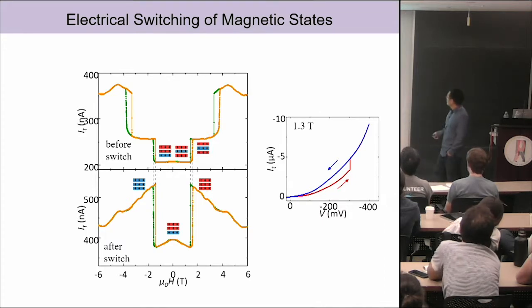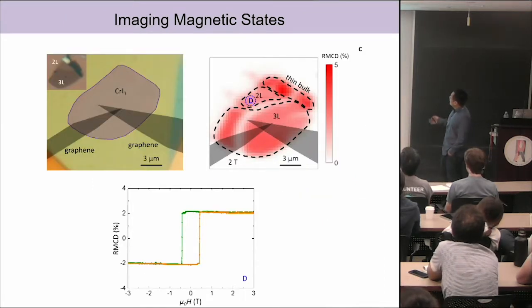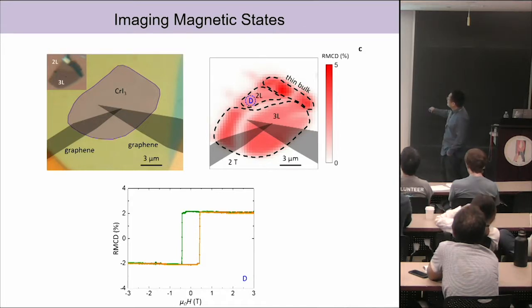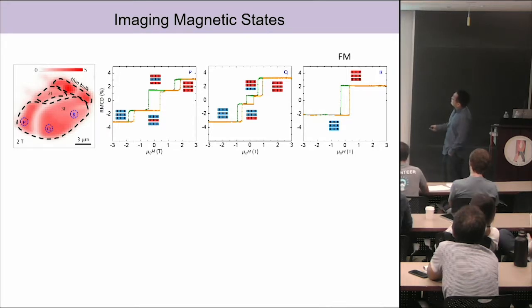All right, and we can also image these magnetic states in real space. So we take the sample out and we do MOKE measurements. On top here, I show the optical image with 2 layers and 3 layers. In this sample, I actually have a 2 layer region there. If I just do a MOKE measurement on these 2 layers, you see ferromagnetic states, consistent with what I showed you. And now if I map the different spots in this trilayer, P, Q and R, we see very different behaviors.